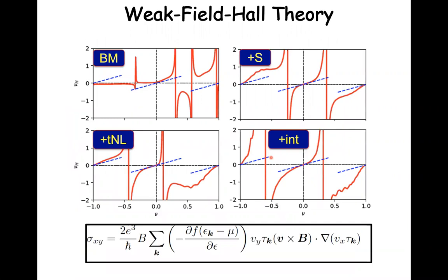So first of all, here's a theoretical calculation of the same thing, of the Hall density. This is just Boltzmann transport theory in the relaxation time approximation. The reason people measure the Hall resistivity is because in the relaxation time approximation, at least, it's a pure band structure property. The scattering rate cancels out. And this is our original band structure model. And these are some improvements on this band structure model I won't discuss, but you can see they're different. And this is maybe the best of these band structure models.